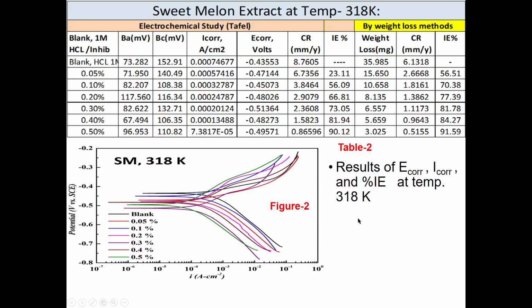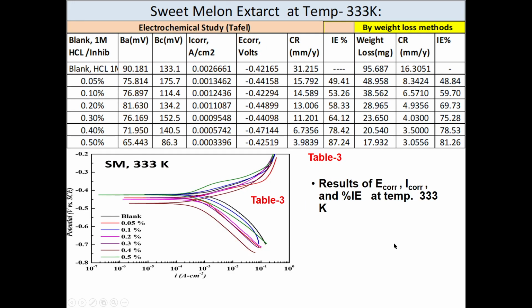And at the other temperature, 318 Kelvin, you can also see that the corrosion rate is decreasing and inhibition efficiency is increasing in both cases, and these are also quite comparable. And at 333 Kelvin also, you can see that the corrosion rate is decreasing and the inhibition efficiency is increasing. So we found similar behavior at this temperature.